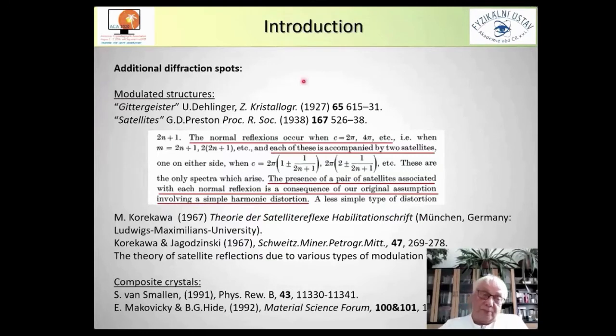The effect of presence of additional diffraction spots was observed even a long time ago. For example, from this paper by Preston, you can see that normal reflections were accompanied by two satellites at these positions, and they have already explanation for this, that the presence of satellites is associated with main reflections are consequence of original assumption involving simple harmonic distortion.